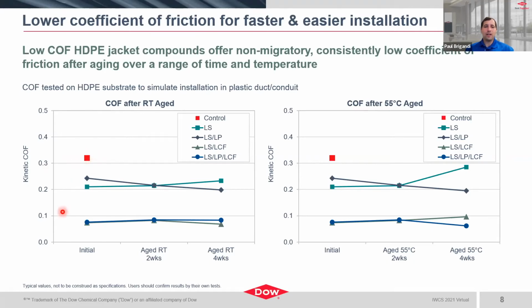Really the key finding here on the materials overall is we're able to drop the COF by about 70% when we look at the low COF samples. We actually see some reduction in the low shrinkage material, so it is an improvement over the control. But really the key is the finding that we can lower the COF by about 70% with the low COF samples. The second key point is, we actually see this stable over time.